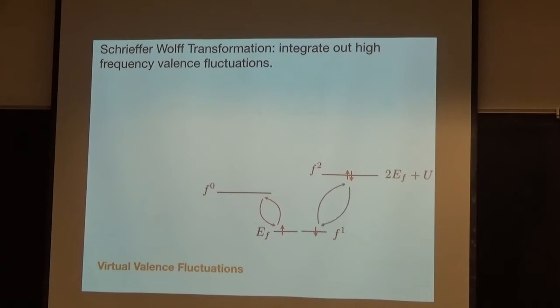And this is what Schrieffer and Wolf did in the early 1960s. They discovered the link between the Kondo model and the Anderson model, and they did so by integrating out the high-frequency valence fluctuations, carrying out a canonical transformation that eliminates the high-energy excitations. This is basically second-order perturbation theory. You can do it in various different ways. But the important point is there's two excitations, one from F1 to F0, one from F1 to F2.